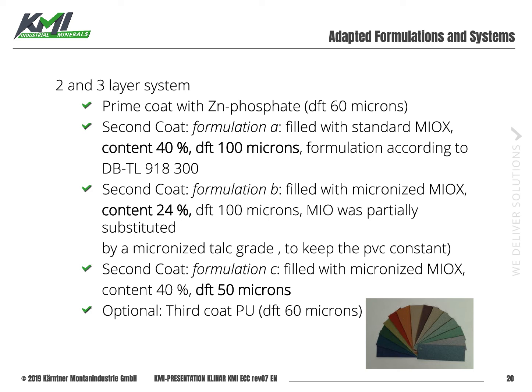With the results of the first test series that the micronized grades outperform the standard grades, we set up a new test series where we again tested 2 and 3 layer systems, again a prime coat with zinc phosphate with a dry film thickness of 60 microns as a prime coat. Then the second coat, there we had 3 different formulations. Formulation A was filled with standard micaceous iron oxide with a loading level of 40% per mass and a dry film thickness of 100 microns.